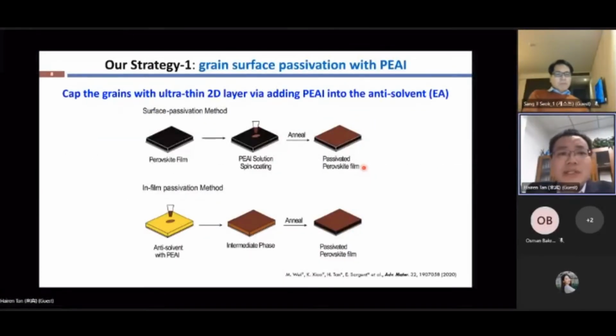So our first strategy started from the year of 2017, when I was a postdoc in Ted Sargent's group in Toronto. I worked with another student and we got an idea: maybe we can cap the grains of the mixed lead-tin perovskite with an organic two-dimensional perovskite material. What we do is different from the traditionally used surface passivation just by spin coating, for example, the long-chain ligands PEAI on top of the perovskite film.